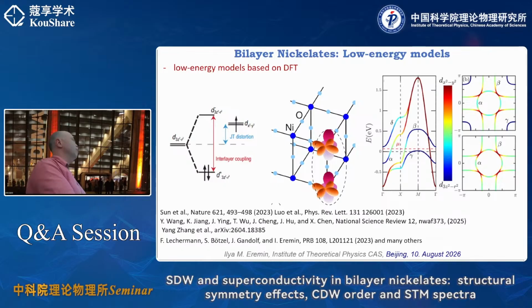It forms also a D-wave or S plus minus gap, but it comes due to the triplon excitation. That's probably an extreme of the model that you start with here, but it has an adiabatic connection, in my opinion, at least a logical connection. Right. So in their predictions, the alpha should have the largest gap. Also, I don't know whether it's really fundamental. Maybe you can twist the parameters and get the larger gap on the beta. It just mediates the pairing from the beta pocket. Yeah, it has a larger density of states.